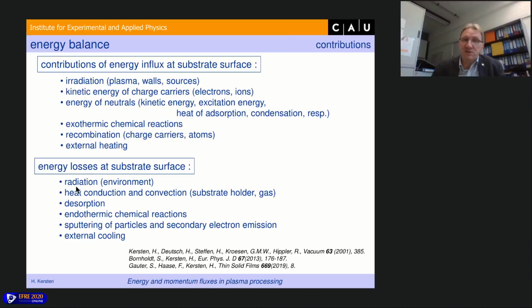On the other hand, you have losses, again radiation to the environment of the substrate, and this is mainly infrared radiation. There might also be heat conduction and convection along the substrate holder and along the gas. There might be desorption into the gas phase. There might be endothermic chemical reactions. There might be sputtering of particles and secondary electron emission, and of course, external cooling. So all these contributions cool the surface. Here they heat the surface and here they cool the surface.